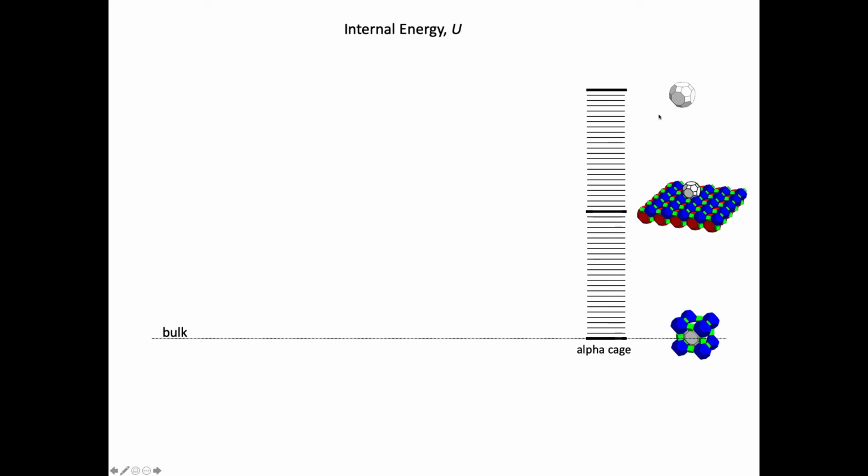So at the top everything is Q3, the bottom everything is Q4. In this particular case there are 49 rungs on this ladder, because there are 48 vertices here which can all be Q3 or Q4. As you switch each one from Q3 to Q4, you drop down 1 rung on the ladder.